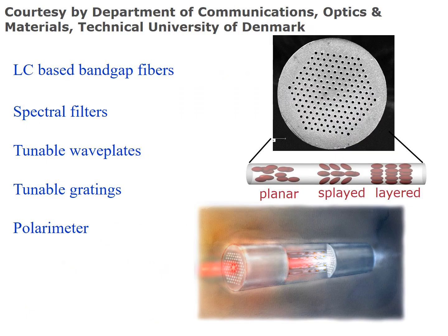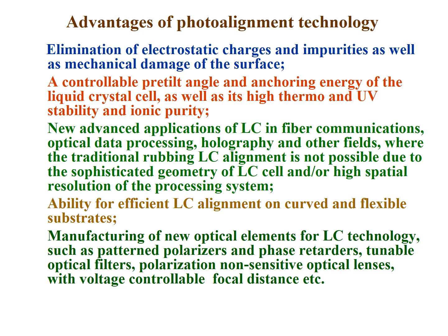And we can foresee many different optical elements in the fibers, like spectral filters, tunable wave plates, tunable gratings, polarimeters, and so on. So, the advantages of photoalignment technology, and in particular azo dye nanosize photoalignment technology: we eliminate static charges and impurities. We have controllable parameters of liquid crystal alignment, like tilt angle, anchoring energy, and thermal and ionic stability. And we can also foresee new applications where rubbing technology cannot be used, for instance, efficient liquid crystal alignment on curved and flexible substrates, and also new liquid crystal photonic elements like patterned polarizers and phase retarders, tunable optical filters, polarization-insensitive optical lenses, and so on.